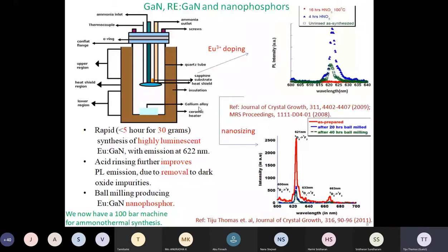And I can nitride it. That means I can flow ammonia at very high temperatures, and then gallium would react with nitrogen. On the surface, I would have gallium nitride. But what would happen is gallium nitride would form a crust, and the remaining part of gallium would remain unreacted. So you have a very tiny conversion of gallium to gallium nitride.